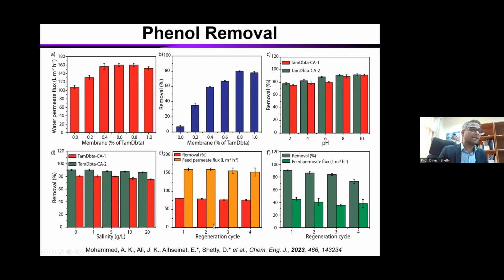It's performing really well. And then we did the regeneration, because if you want to reuse it, you have to regenerate it. We also checked after regeneration whether the membrane maintains the same flux or not. So all in all, this is not direct separation, it's adsorption. When the phenol passes through the membrane, it interacts with the pillars within and gets stuck there, adsorption basically, then desorption, and it allows water to go through. That's how we are removing phenol.